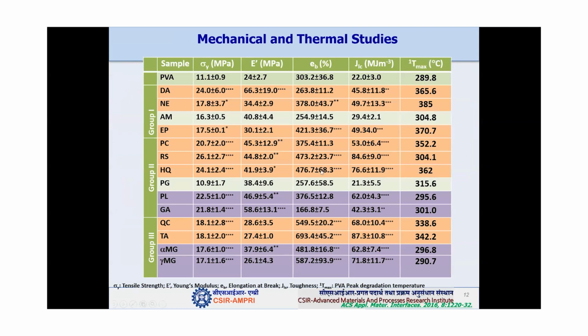Then these are the mechanical and thermal properties of all these films of different categories. This is the pristine PVA, and this is with the compounds, and this is our yield strength, then Young's modulus, then elongation at break, and then toughness, and then we are measuring the thermal stability. And we found that after adding most of these compounds, particularly the ones highlighted in orange color and the ones highlighted in purple color, we are getting very good enhancement in the mechanical and thermal properties. So somehow these compounds are helping in enhancing the mechanical stability as well as the thermal stability of the films. So this is another benefit for us if we are thinking of designing packaging material or some other antimicrobial film based application.